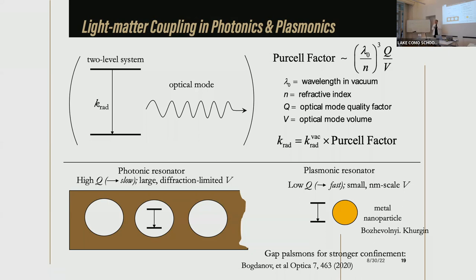In plasmonics, Q is modest, just 100. But that's actually good news. It means that the quality factor would be like 100, meaning that the bandwidth would be terahertz, like 10 terahertz. But that indicates the speed. That's what we're after. Whereas volume, to compensate for small Q, could be really small. 5 nanometers, as I mentioned. 5 nanometers is 100 times smaller than the wavelength. You raise it to the power 3, because it's volume here, it gives you a million. Only because of confinement, light-matter coupling could increase by a huge factor. And in this case, you don't sacrifice the speed. Your system is fast and potentially could outpace the rate of decoherence. That's the simple idea which we're after.